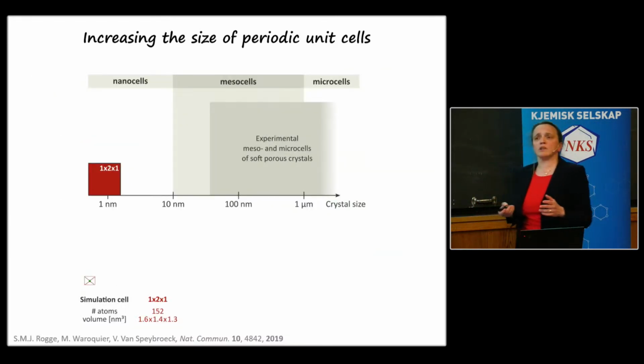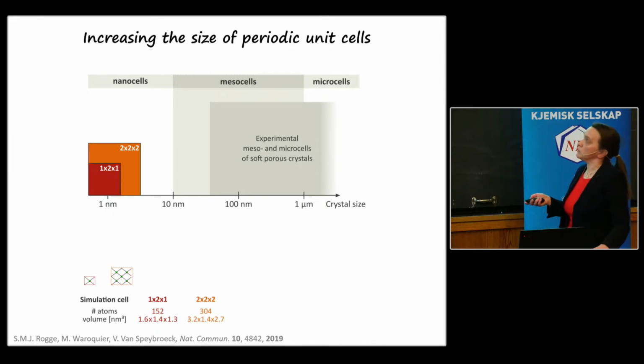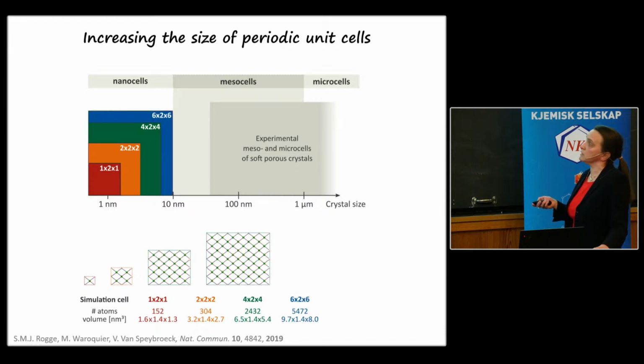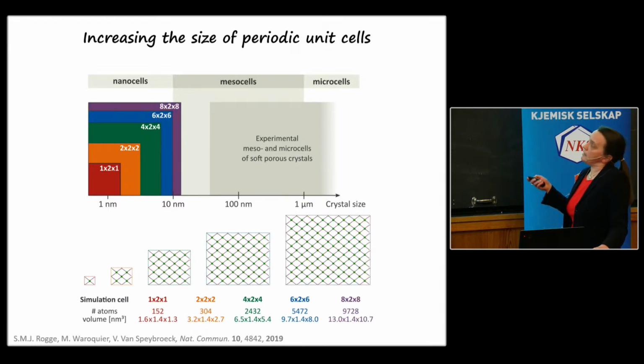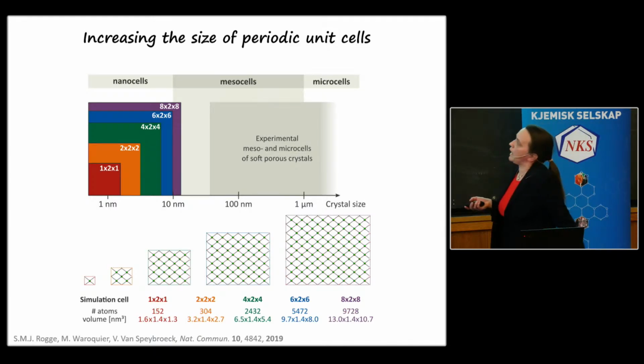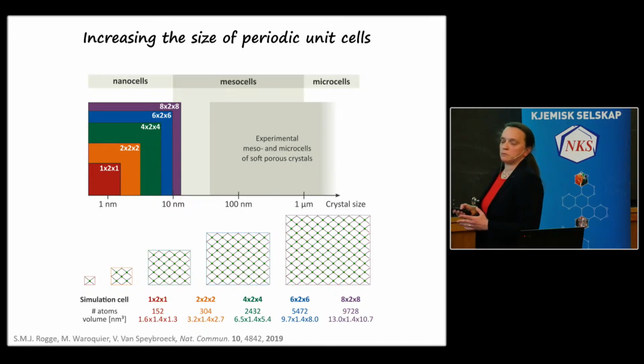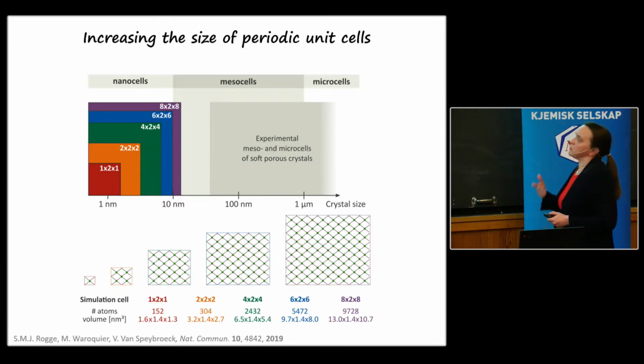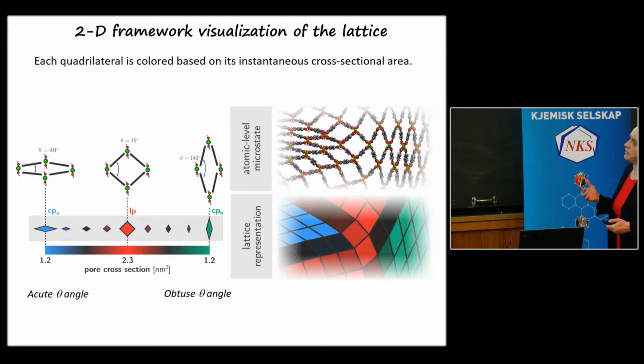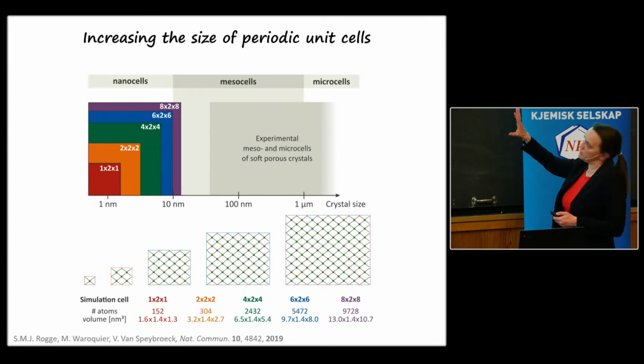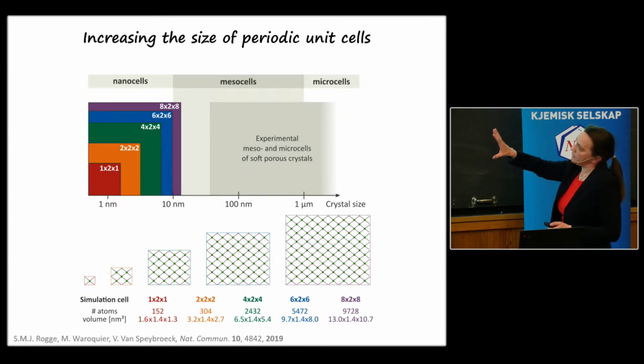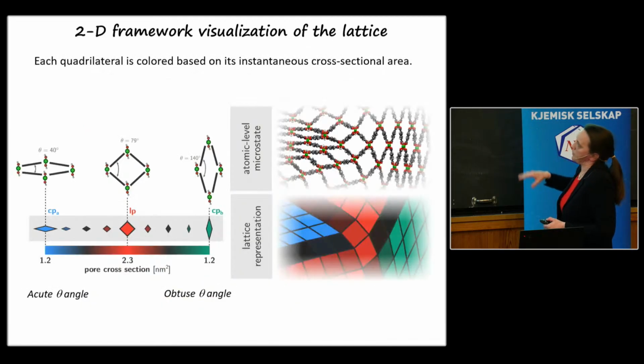Then we said, okay, let's increase the size. How far can we go? We start to increase the size of the system. At a given point, that was in 2019, we went to crystal sizes of about 10,000 atoms. Then we do the same exercise again, and we try to see whether we see other mechanisms depending on the crystal size.